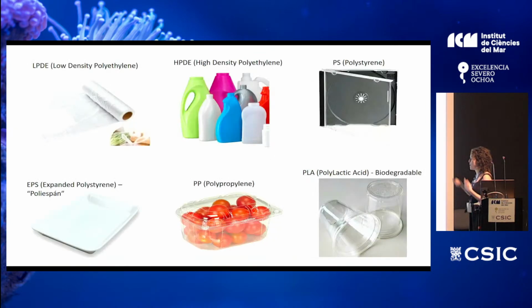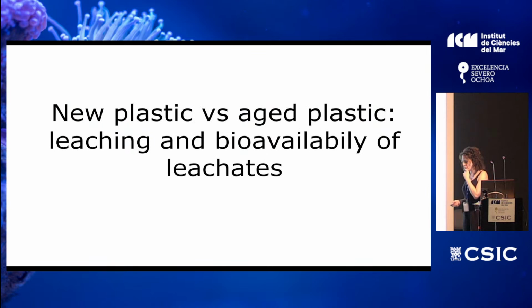So these are the plastics that I introduced to you before that we use in all these experiments. And the first question we had was regarding the degradation stage of the plastic. Because most of the studies that have been made with leachates have been made with new plastic that is not degraded. But most of the plastic that is found in the ocean is already degraded, it's weathered. It has been exposed to sunlight, it has scratches and everything. And we wanted to know if that aged plastic, which is more realistic to what we find in the ocean, would be releasing more or less dissolved organic matter than the new plastic, and if the material released was more or less bioavailable to microbial uptake.